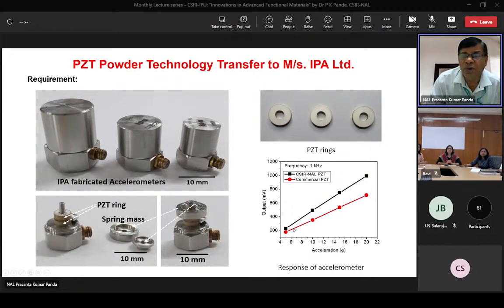Now, the output voltage was high in our case, particularly the NAL prepared. As you can see, for any acceleration, the level of output in millivolts is much higher. About 1000 millivolts compared to the commercial PZT, which generated about 600 to 700 millivolts. Moreover, and most important, is the linear behavior of this output voltage at different accelerations. That is what made the company decide to go for our PZT powder technology.